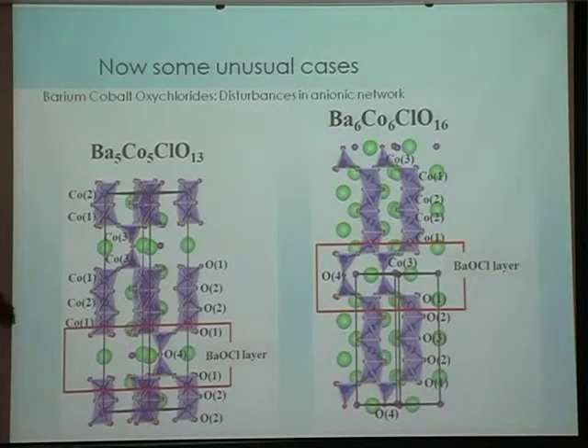And of course, the structure says that it's not cubic. It's some kind of hexagonal structure with rather complex distributions. Like you have octahedrons, cobalt oxygen octahedra, sharing a face. And they are connected to the next set of octahedra via a couple of tetrahedra, cobalt oxygen tetrahedra.